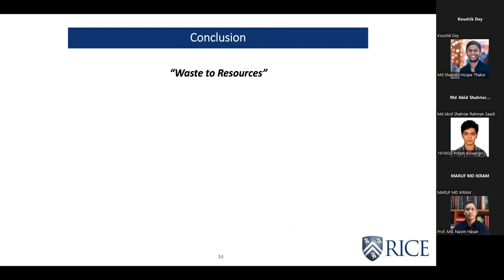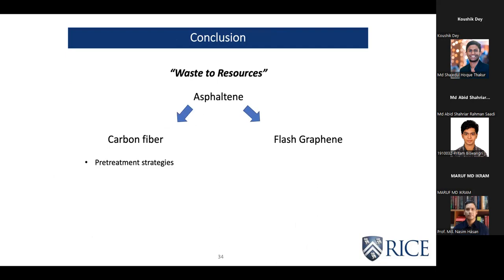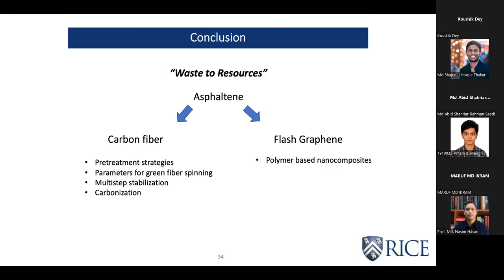Basically, in our effort to convert a waste resource, we have taken asphaltene and converted it into carbon fiber and flash graphene. For the carbon fiber, we developed several pretreatment strategies. We determined the parameters needed for green fiber spinning. The multi-step stabilization routes that I showed were our own original idea. We came up with these multi-step stabilization processes that worked really well, that helped us do carbonization and get nice fibers with good mechanical properties. For the flash, after successfully converting to graphene-like structures, we developed these polymer nanocomposites, which had good mechanical properties and thermal properties.